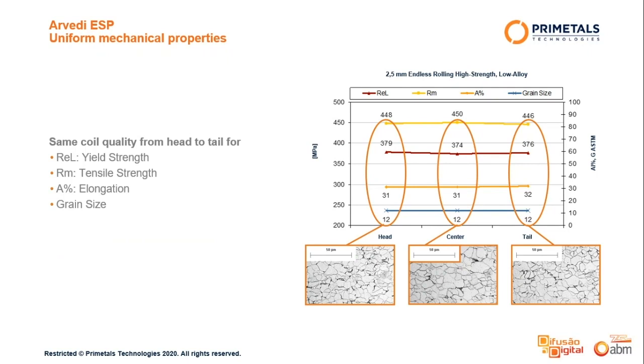Most appreciated from processors is the fact that ESP material shows uniform mechanical properties from head to tail. There is no difference in yield strength, tensile strength, elongation or grain size. Of course, the plant never sees a head or a tail, and the strip is never influenced by speed ups or other operational requirements as known from coil to coil rolling.